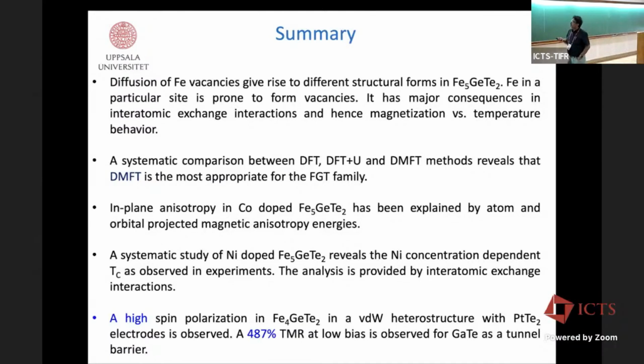For cobalt doping, the in-plane anisotropy we could explain by atom-resolved magnetocrystalline anisotropy energies. For nickel doping, we could reproduce this peculiar behavior of TC as a function of nickel concentration. And finally, around 500% TMR at a low bias was observed for this particular van der Waals heterostructure.